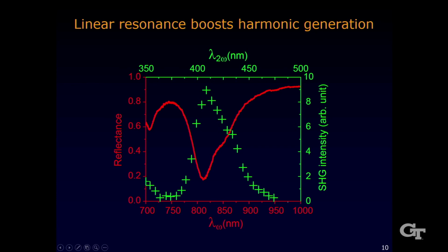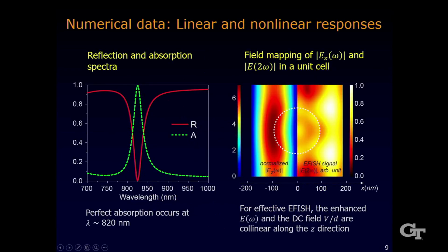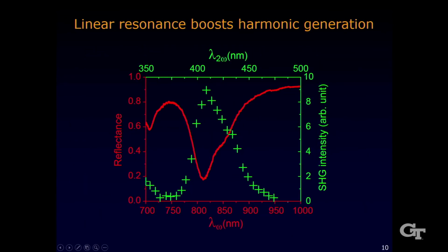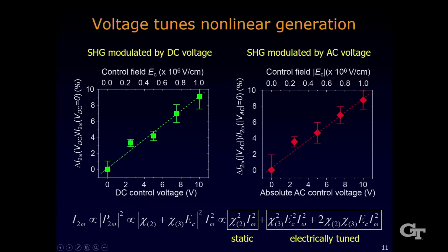So here you can see, even without applied field, you do see some harmonic generation from the system because there's always some surface effect. And more importantly, the conversion efficiency reached the peak level at around 820 nanometers. This is precisely where this structure is designed to function. So we are going to fix the wavelength at this excitation wavelength and then use a voltage level to tune the harmonic generation of light from such a device.